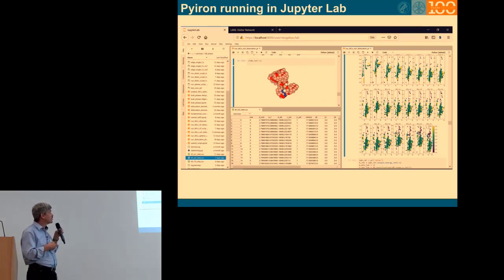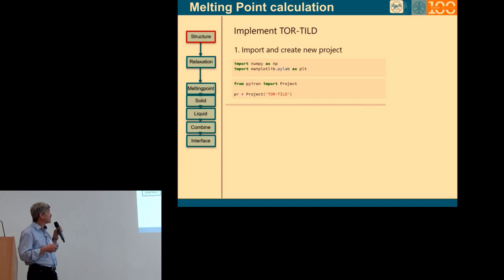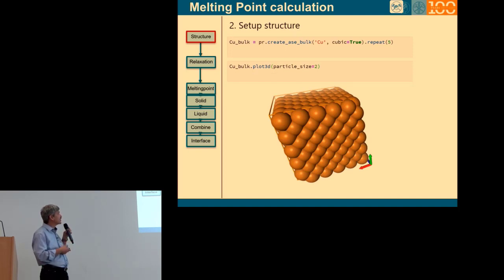When seeing these type of graphs I quite often realize it's difficult to see what is behind and I was thinking it would be good to show one simulation protocol, how this is actually working. And the example is parts of the melting point calculation. In order to run this we have first to start with a structure, perform some relaxation, get the solids into high temperature, go above into the liquid temperature, melt the system, combine it and then we can look at whether the liquid is expanding or the solid expanding. So how to realize this would be this type of protocol. And in order to run this type of simulations we have the pyiron tool which is implemented in Jupyter Notebooks or in this case JupyterLab. We have the file browser, we can look at different data, we can visualize the structures and just to show how this works in practice I thought I'd show parts or pieces of this example.